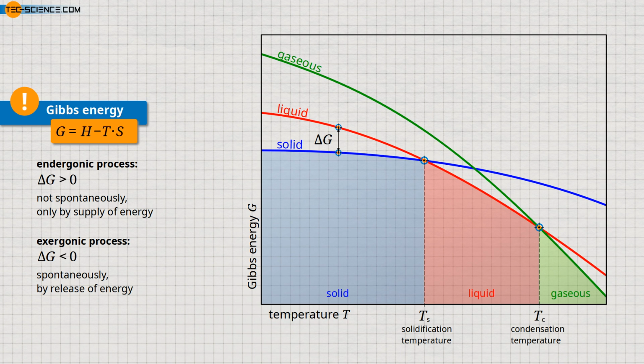This fact already shows that simply reaching the solidification point is not sufficient to cause a liquid to solidify. A drive for solidification is only given if there is a difference in the Gibbs energy and thus a drop below the solidification temperature. Therefore, a so-called supercooling is necessary. The latent heat of transformation during the phase transition can also be determined from the diagram. For example, the difference in Gibbs energies between the solid and liquid states at absolute zero corresponds to the enthalpy of solidification of the substance. In the same way, the enthalpy of condensation can be determined from the difference in Gibbs energy between the liquid and gaseous states at absolute zero.